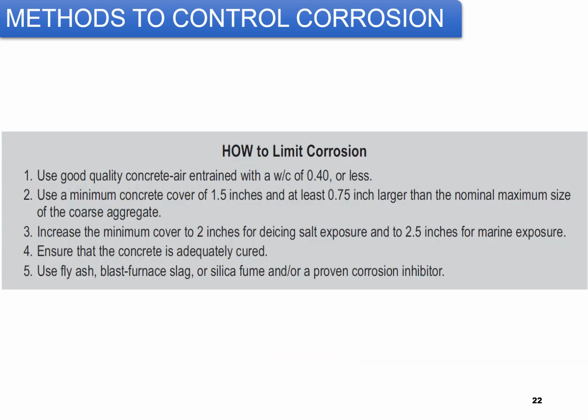So how to limit corrosion? Use good quality concrete, air entrained, with a water cement ratio of 0.4 or less. Use minimum concrete cover of 1.5 inches or at least 0.75 inches larger than the nominal maximum size of the coarse aggregate. Increase the minimum cover to 2 inches for de-icing salt exposures and 2.5 inches for marine exposures.